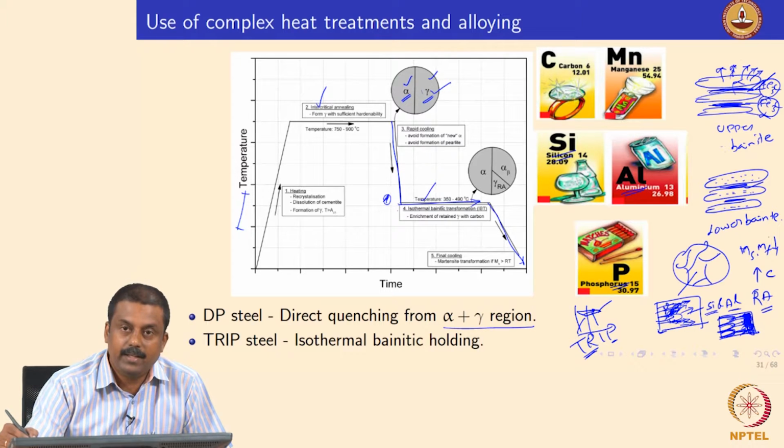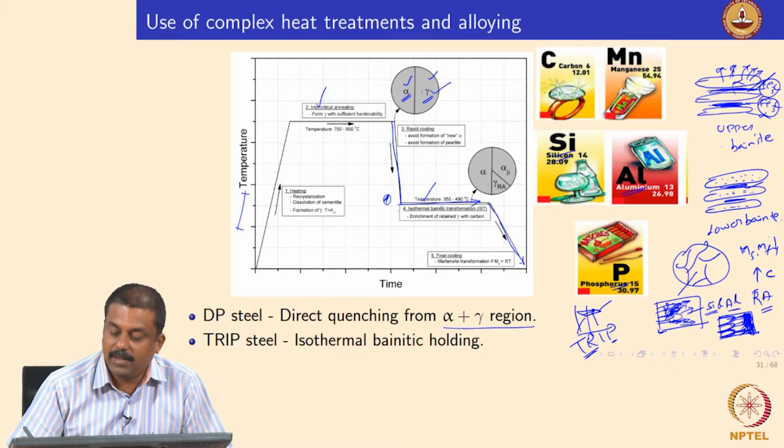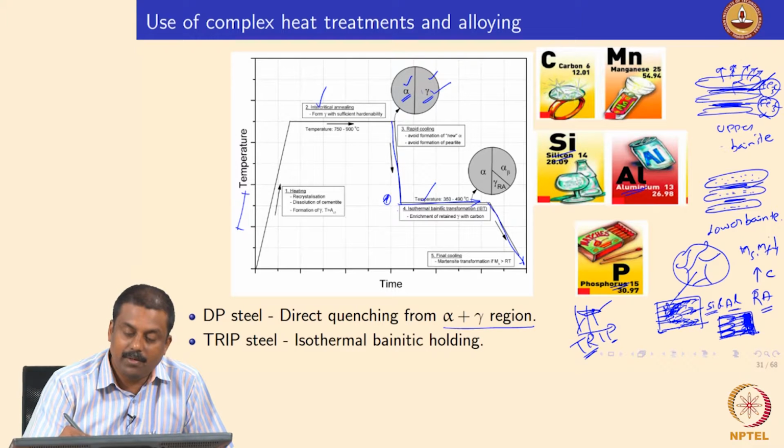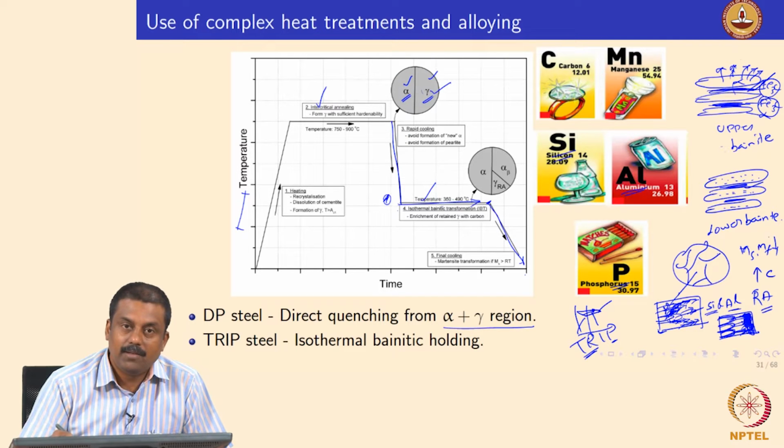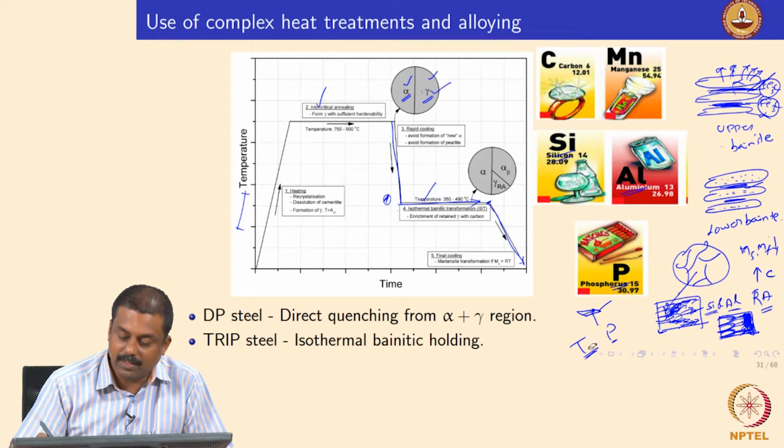Therefore, when the bainite forms, it is just forming as a single phase, bainitic ferrite, without the nucleation of cementite, and during this process, we all know that the solubility of carbon in ferrite is much lower. So, the carbon has to go out to the untransformed austenite, is it not, and this untransformed austenite is getting enriched in carbon, and upon sufficient enrichment your MF temperature would go below room temperature. So, subsequently when you cool down to room temperature, your austenite would be stabilized. Yes, it is clear.